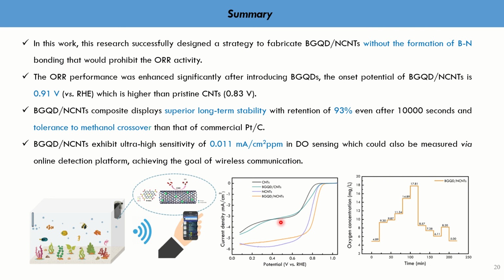So, in summary, BGQD/NCNT can be synthesized without the formation of boron-nitrogen bonding and also has a great onset potential. BGQD/NCNT also has superior long-term stability to platinum and a great retention. BGQD/NCNT also exhibits ultra-high sensitivity compared to others.